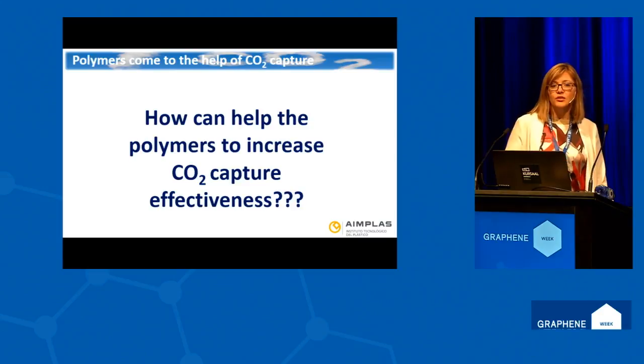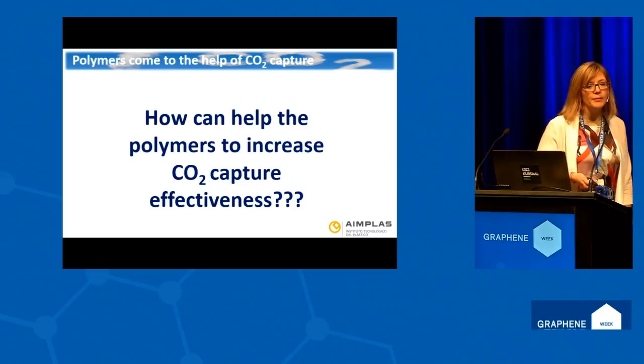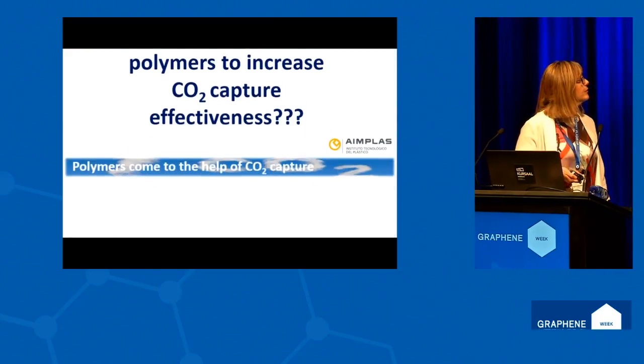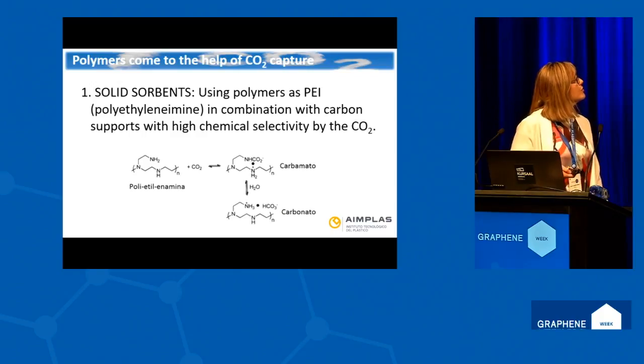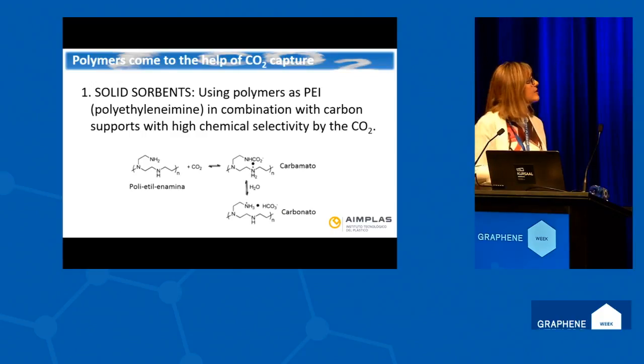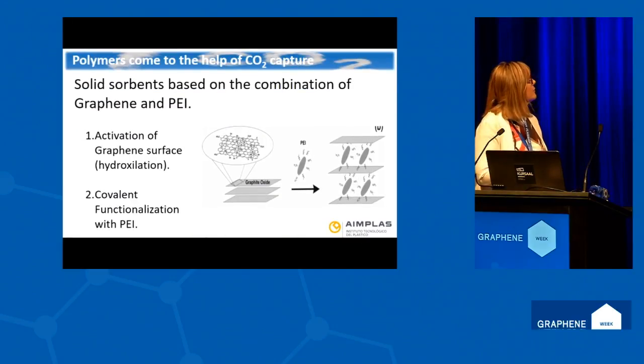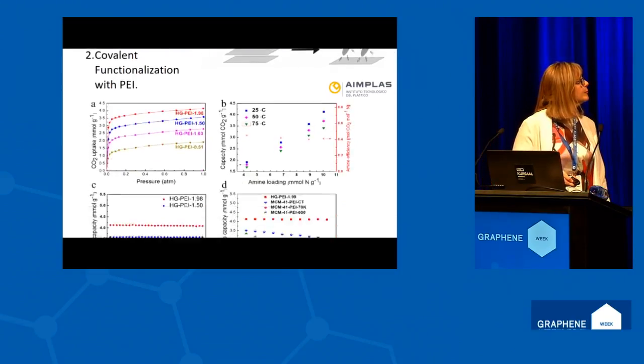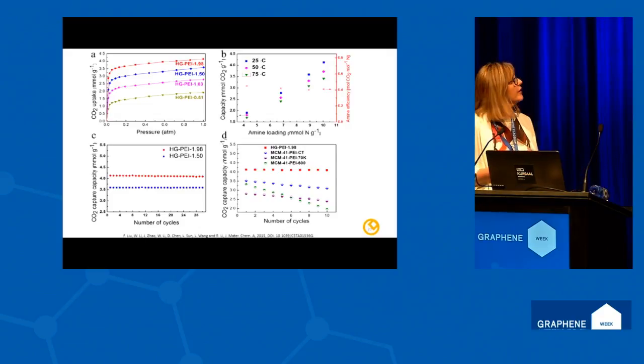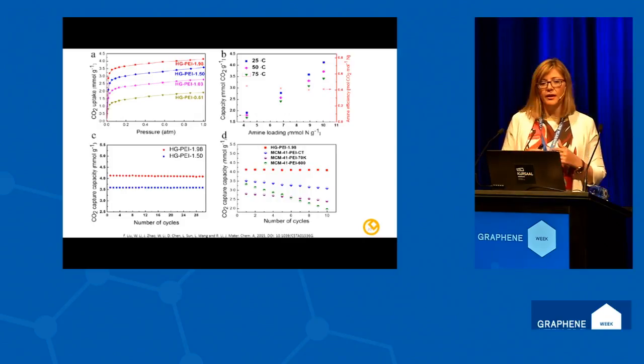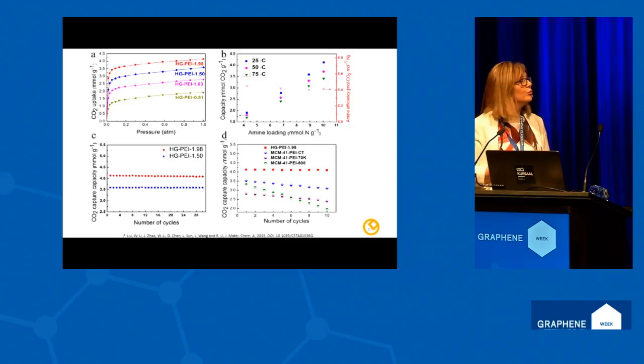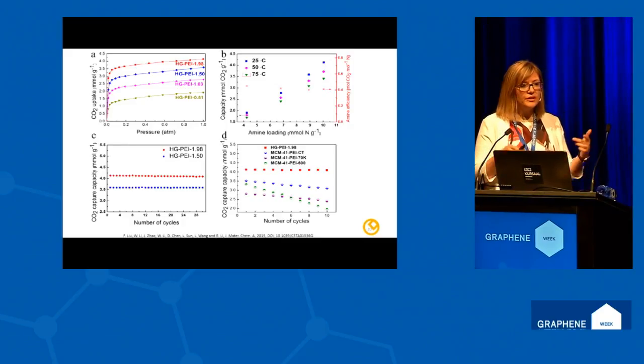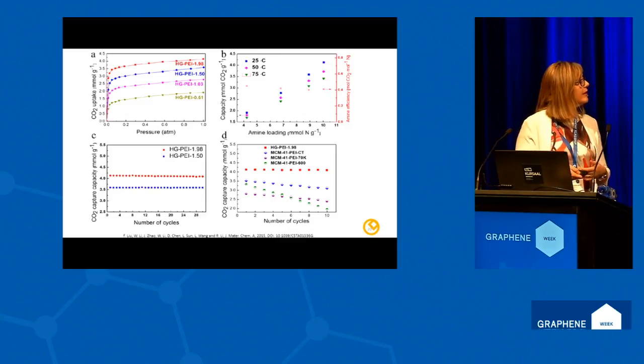So let's move on. Another possibility is to help to increase the effectivity using polymers together with the carbon structures. So we can use solid sorbents combined with PEI, for example. We can activate the surface of the graphene, and after that functionalize with covalent bonds with PEI. These are some results so that you see that when we increase the content of PEI, we increase the capture of the CO2. And also the number of cycles, when we use this and regenerate, we can maintain the effectivity.